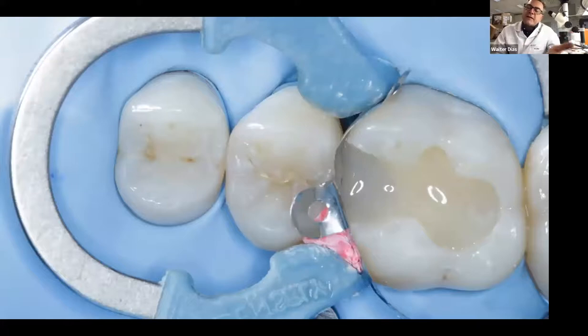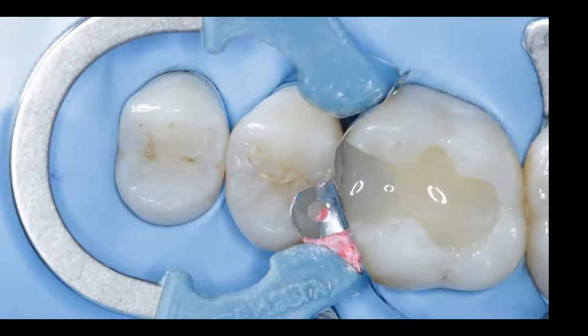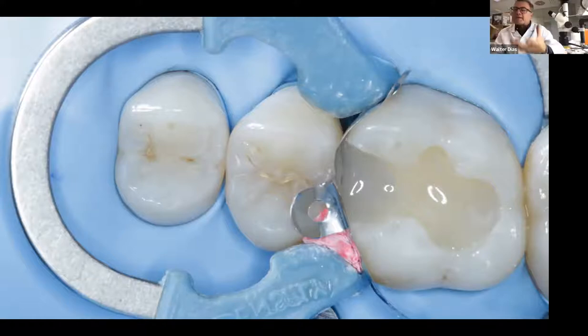This is direct, so that's why we applied a little more on the proximal box, but you could apply a little less and have a thinner layer. But this is the idea of immediate dentinal sealing. You're going to seal the whole dentin before you apply the composite, or even before you do your preparation. Because now, let's say if this were an indirect case, you would then prepare this and scan it.